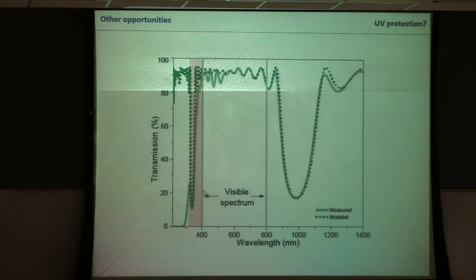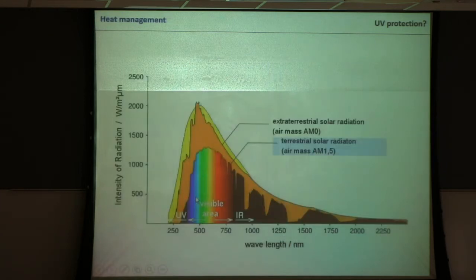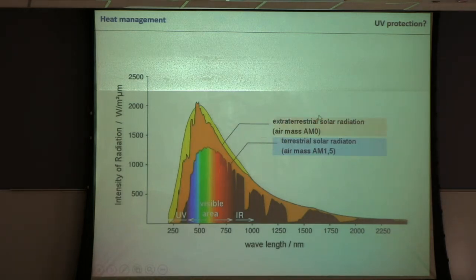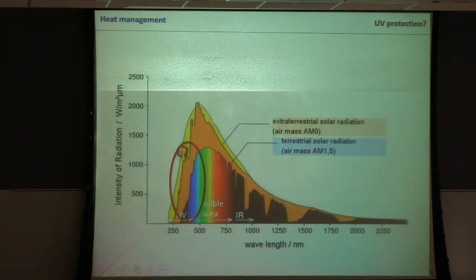Most UV protection layers usually absorb the UV, but therefore they also degrade over time. Here we have a system where we can nicely manipulate the UV reflection. There are of course many options, maybe not on the building, otherwise we just reflect all the UV on people. That's maybe not a good thing. But where we really could have potential for such mirrors is in extraterrestrial radiation. When you compare the UV on Earth and outside in space, you see there's a big difference. Here we are shielded, at least at the moment still, from the UV, but outside not. So wherever you need solar cells working outside, this could be an option.